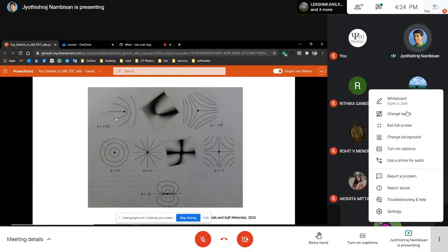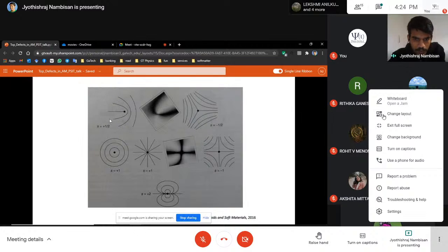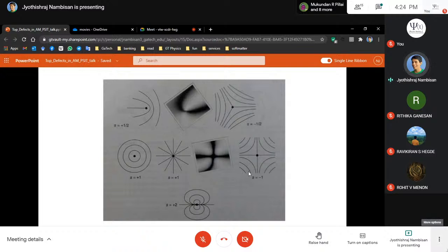So a different charge defect. This one is a plus half. The plus half has a very distinctive comet-like shape, and under a polarized microscope, it looks like that. The minus one half has threefold rotational symmetry. The plus one is when you have a defect and you go around it 360 degrees and you end up in the same configuration. So that's perhaps easiest to imagine. The minus one half, and some of these vector fields actually correspond to some of the fields that you solve in your math methods or IDC courses, your divergence and curl fields. So there are parallels between that as well.